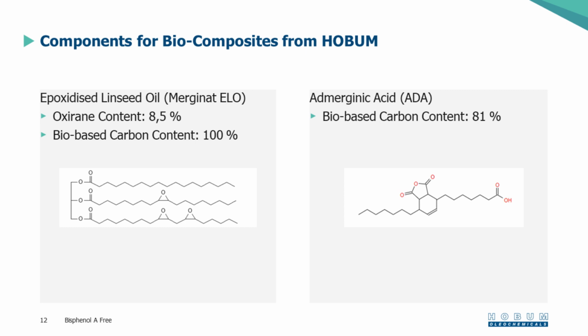It's also possible to use our epoxidized linseed oil. It has an oxirane content average of 8.5, and the bio-based carbon content is 100%. Of course, the oxirane rings in an ELO are less reactive than the glycidyl ethers of bisphenol A resin, but at a certain point they will react and will form a nice network.